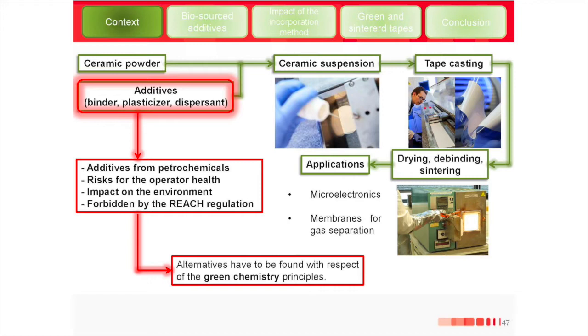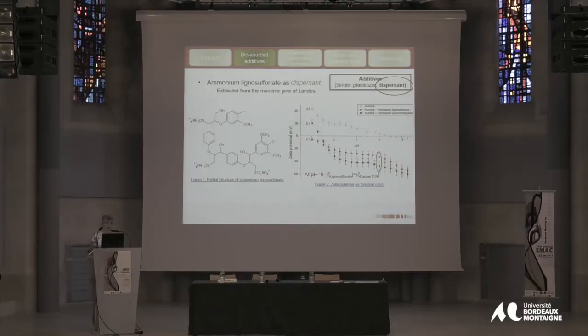The way to check if a dispersant is efficient or not is to measure what we call the zeta potential, which is the surface charge of the particle, as a function of the pH. So in that case, it's an alumina powder. Alumina powder alone in water, pH is 9, but because there is no surface charge, there is a sedimentation, so it's not very good to prepare a good suspension.